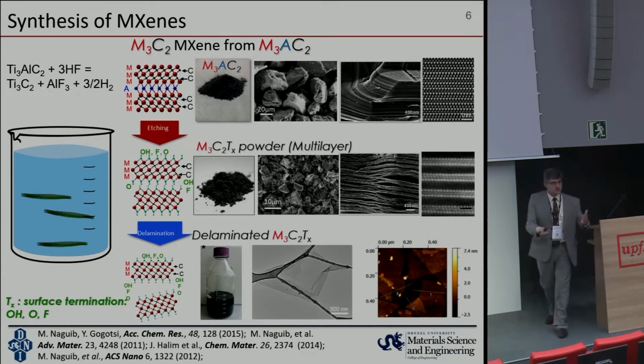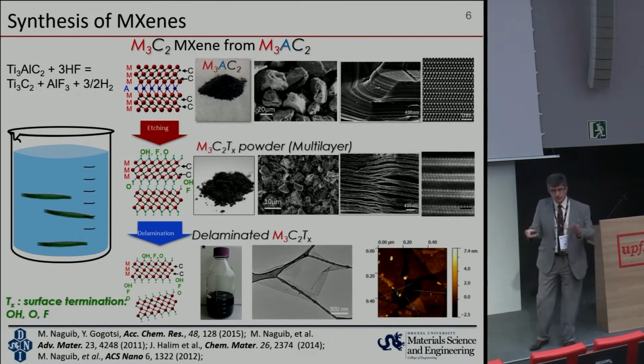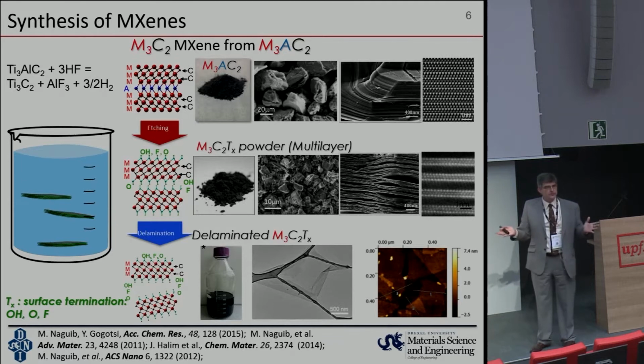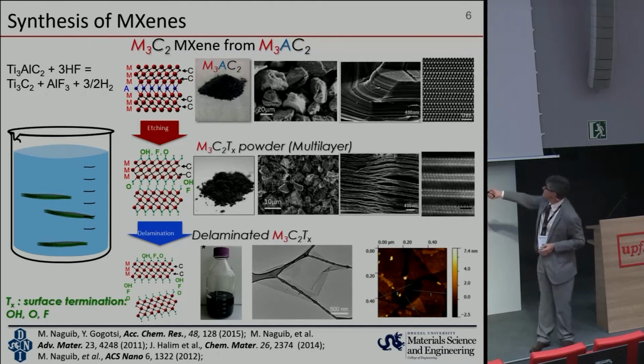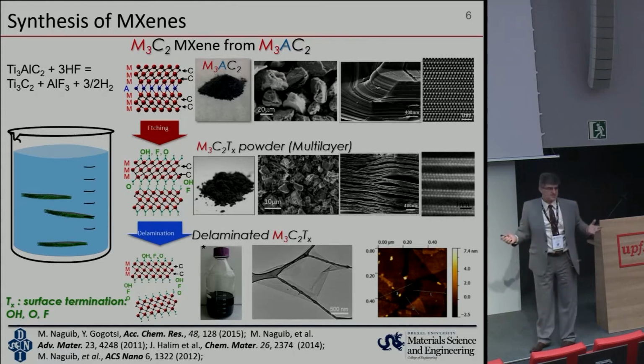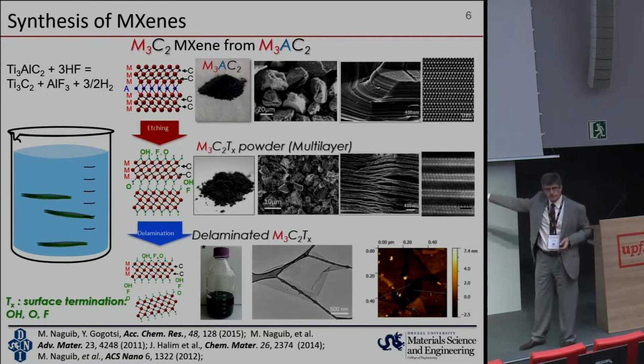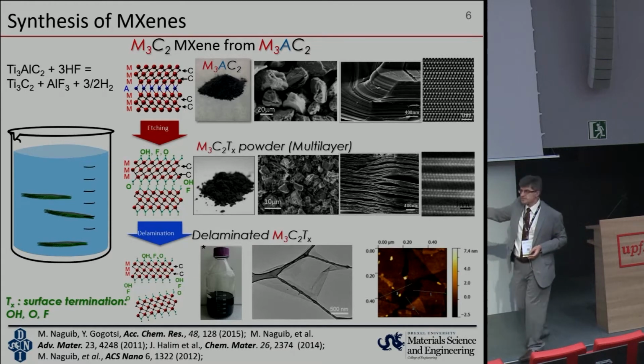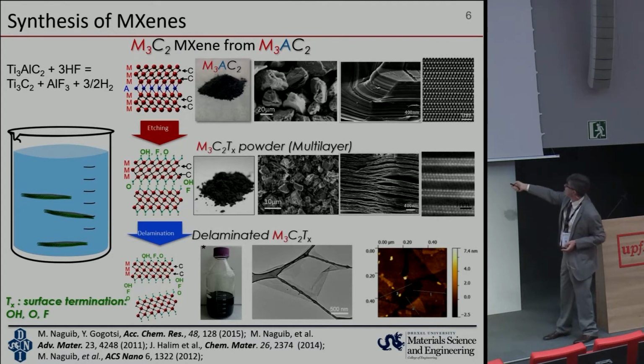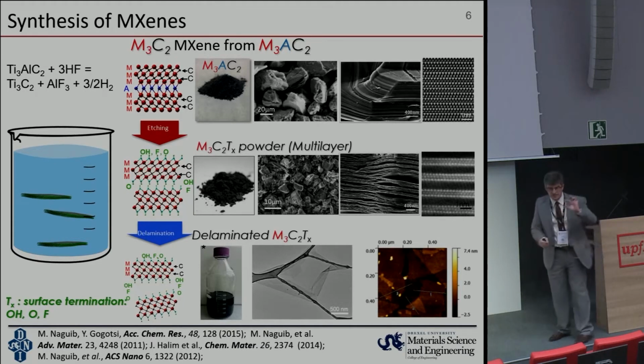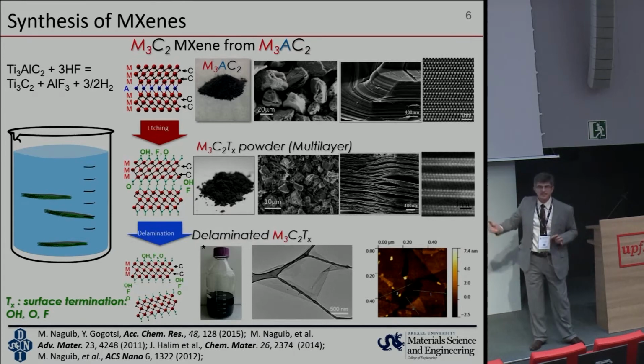Naturally, now we have a precursor just like clay or LDH, where we can very simply, by either sonication or intercalation and sonication, and often just simply by twisting a bottle with a solution several times, delaminate it into single layer flakes. This is a 1 liter bottle with about 400 milliliters of solution of Ti3C2, and these flakes all look the same. I can tell you this is graphene or molybdenum disulfide or boron nitride. You will have to believe me, they're pretty much the same. But atomic force microscopy shows that all flakes are about 1 nanometer in thickness. So we have here single layer MXene.